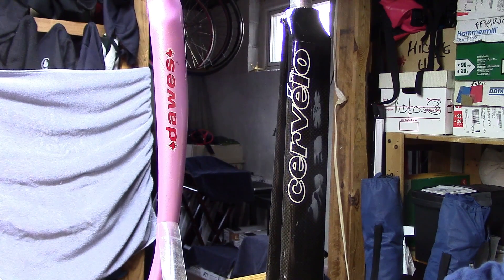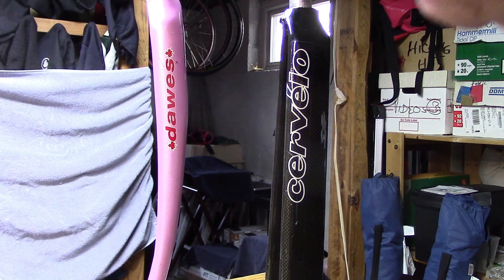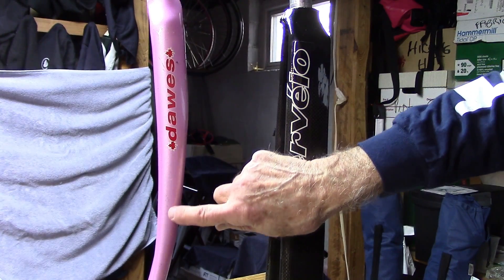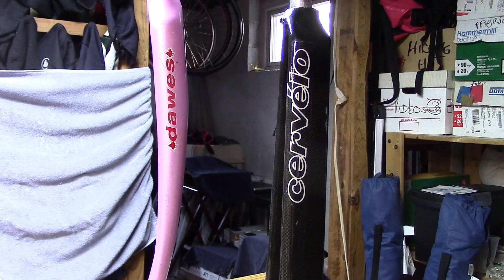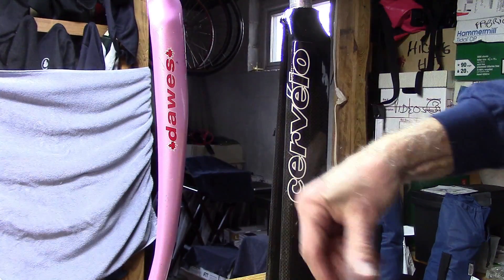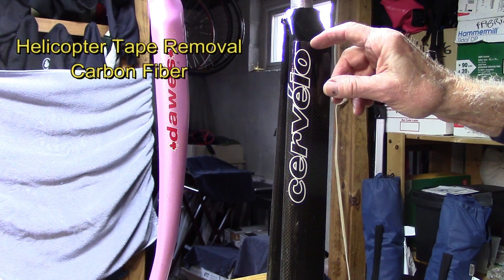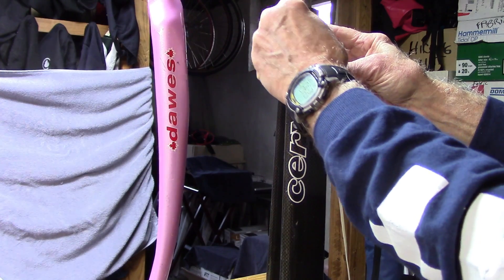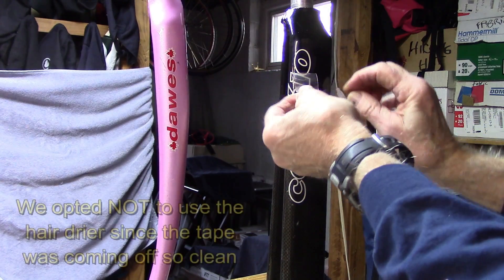Using the hair dryer, it actually comes off easier. Any marks that you may see were marks that were already there. The tape itself looks pretty good, so I don't think we've removed any of the clear coat or paint with the helicopter tape. Now we'll turn our attention to the carbon fiber fork. We'll do the same thing, only holding the hair dryer a little further back on the bottom half so we don't damage the underlying carbon fiber. It comes off very nicely and very clean.